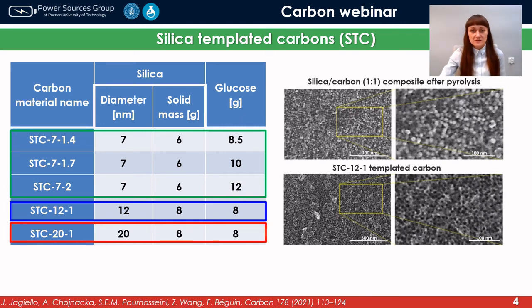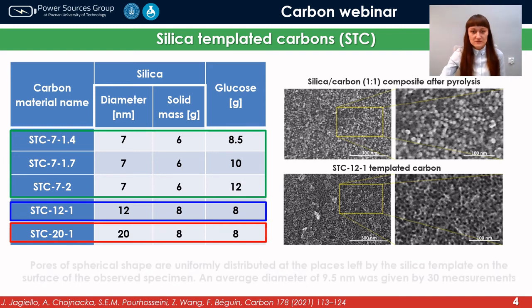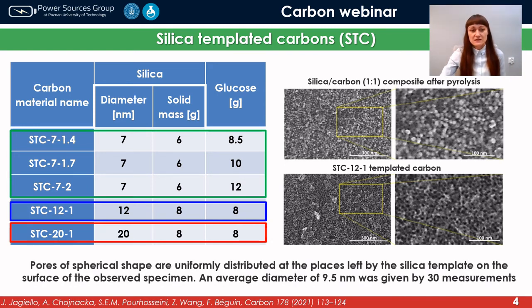And the example silica carbon composite after pyrolysis, and also the resulting templated carbon, in which we were using the silica diameter of 12 in our precursor mixture, is shown on the right. And as you can see, the pores of spherical shape are uniformly distributed at the place left by the silica template, and by 30 measurements we established that the average diameter of the pores is around 9.5 nanometers, which is very close to the value given by the producer.